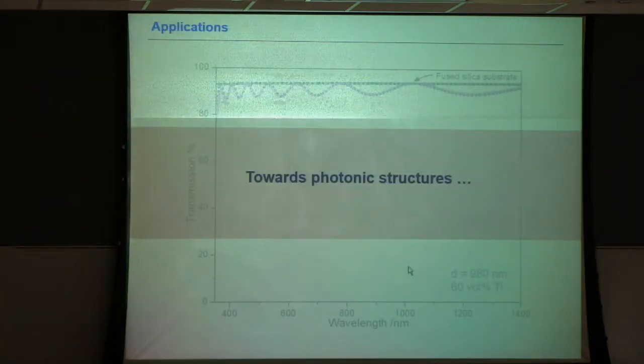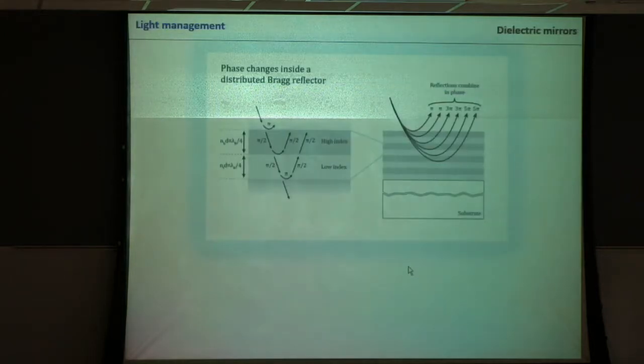Okay, now we finally have a plastic that we can use, hopefully, to guide light. So what shall we do? We started to make the most trivial, I think, photonic device, a simple dielectric mirror, a Bragg reflector. So here you just have a multi-layer structure of a high refractive index material, our hybrid, and a low index material. Clearly for polymers, the choice for the low index is actually pretty large. For the high index, we used a medium range content hybrid.